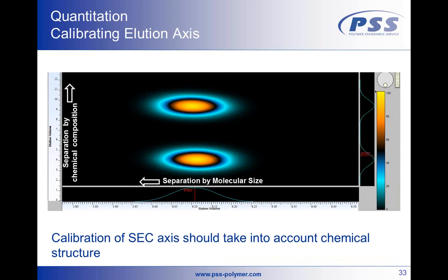In addition, if we talk about polymers, we would like to get molar masses typically. And if we do a separation, then first the separation in this direction might be according to chemical composition into the y direction, and you have two peaks, but these are chemically different species. So what we would like to have is a method to determine the molar masses. From the first glimpse, we would say both have identical molar masses because they elute at the same elution volume. But as you know, size exclusion separation is based on molecular size and not on molecular mass. So we should apply a different calibration curve for this peak than for this peak. And that can be done.